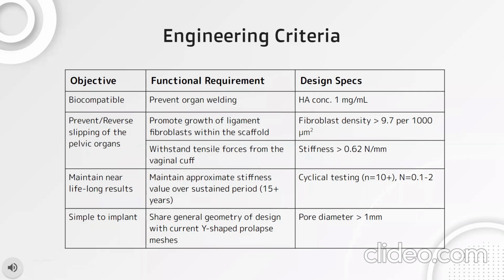Next, our device should prevent and reverse any slipping of pelvic organs. Therefore, we need this device to promote the growth of ligament fibroblasts within the scaffolding by having a fibroblast density of greater than 9.7 per 1,000 micrometers. Additionally, our device needs to withstand the tensile forces from the vaginal cuff, requiring a stiffness of greater than 0.62 newtons per millimeter. Third, our device must maintain a near lifelong result, so it must maintain the approximate stiffness values for 15 or more years.